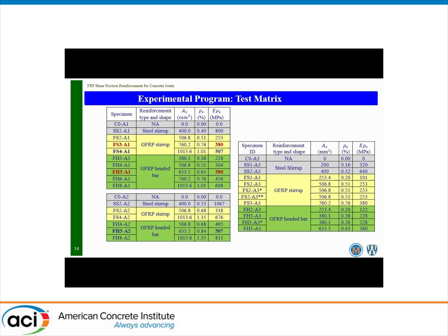Also, with two interface areas, 250 by 500 or 250 by 300, we have two specimens with the same stiffness modulus, or stiffness factor, as we call it.